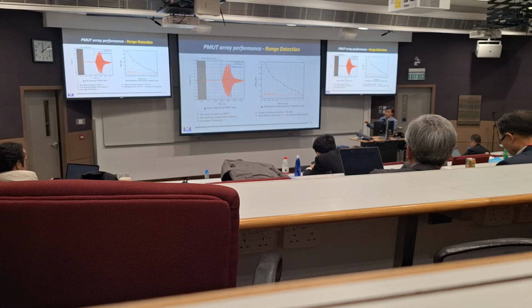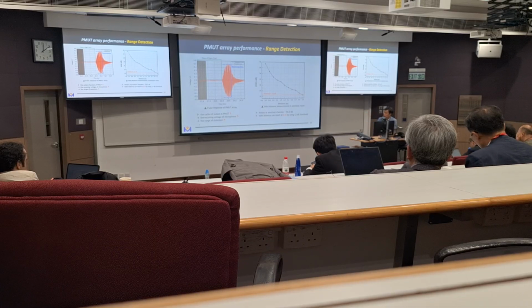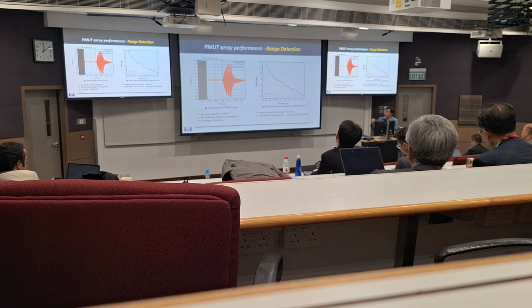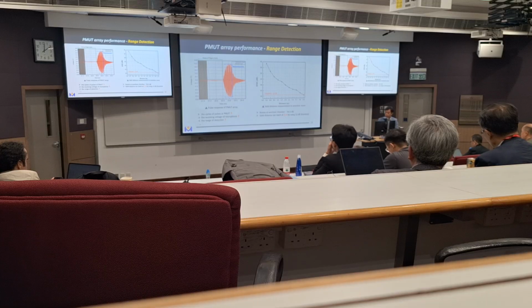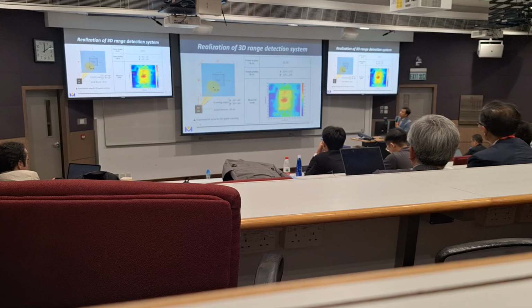And from the threshold for signal-to-noise ratio, we can conclude that the sensor works quite well, and the theoretical range we can reach is around 3 meters. And this is the final calculation.